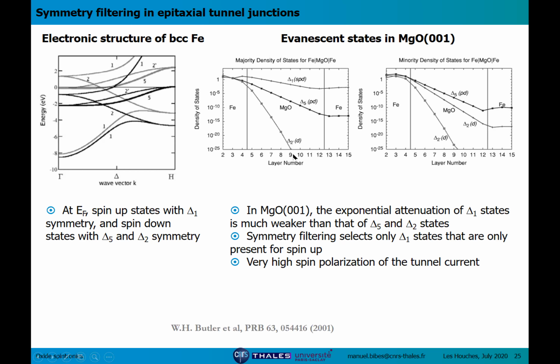Okay. So because in the iron for spin up, you only have delta 1 states, and you don't have delta 1 states for spin down, that's very important. The delta 1 state will be predominantly transmitted by the MgO barrier, so that effectively at the output of the MgO barrier, you will almost only have delta 1 states present. And because these delta 1 states are only present for the spin up, you will only have spin up states. And so this kind of symmetry filtering of the tunneling wave functions is going to result in a very strong increase in the effective spin polarization of the tunneling current. So here you have symmetry filtering that enhances very strongly spin polarization.